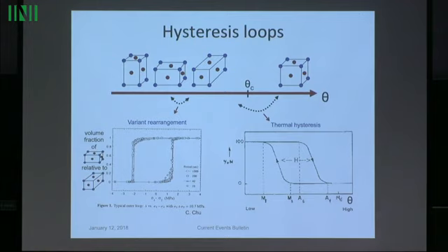And the reason I put this diagram there is this was measured with a period of the loading of 10 seconds, 40 seconds, 200 seconds, 1,000 seconds, so varying by 2 orders of magnitude. And the hysteresis loop was very much the same.